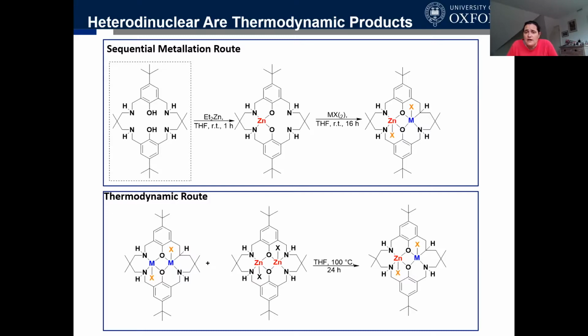And we do so free from contamination by the homodinuclear because that heterodinuclear species is thermodynamically more stable. In order to prove that, we can also establish that by taking zinc and magnesium and heating them together over a prolonged period of time. Then what happens is that we have exchange of the metals, hot and over a prolonged period of time. And then we end up with ever increasing quantities of the heterodinuclear species.